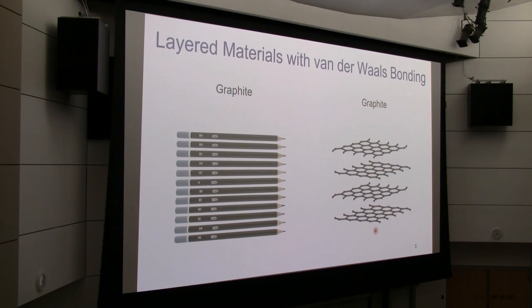So the best known and most ancient Van der Waals material is graphite. People actually made it into pencil and use it to write. So when you write on your paper, what you are doing is exfoliating this structure on the right, where you have these strongly bonded layers that are covalently bonded. But between the layers, they have very weak interaction. They have basically Van der Waals bonding. And when you write with the pencil, you can basically break this Van der Waals bond and you can cleave the thin layers. So a question that people started to ask is, if we can cleave this thinner and thinner,